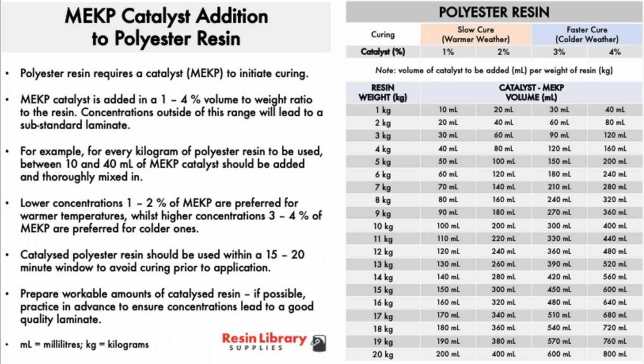Polyester resin requires an MEKP catalyst to initiate curing. MEKP catalyst is added in a 1 to 4% volume to weight ratio to the resin. Concentrations outside of this range will lead to a substandard laminate. So for every kilogram of polyester resin to be added, add between 10 and 40 milliliters of MEKP catalyst and thoroughly mix it in.